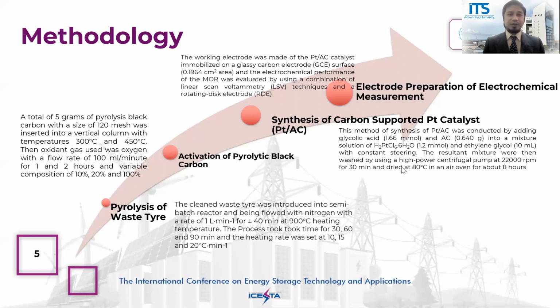The resulting carbon-supported platinum catalyst was applied in DMFC, particularly in the methanol oxidation reaction. The working electrode was made of the platinum activated carbon catalyst immobilized on a glassy carbon electrode, and the electrochemical performance of MOR was evaluated by a combination of LSV and RDE.